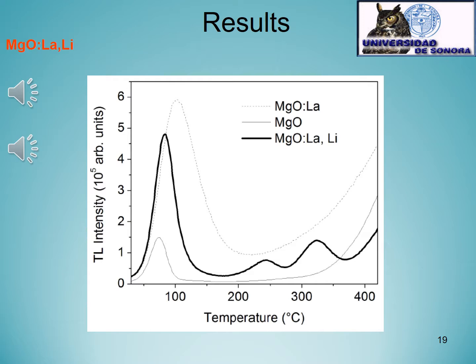In this graph we can observe the difference between TL glow curves of pure magnesium oxide, lanthanum doped, and magnesium oxide lanthanum lithium doped. So for the co-doped sample with the lanthanide and lithium, we can observe